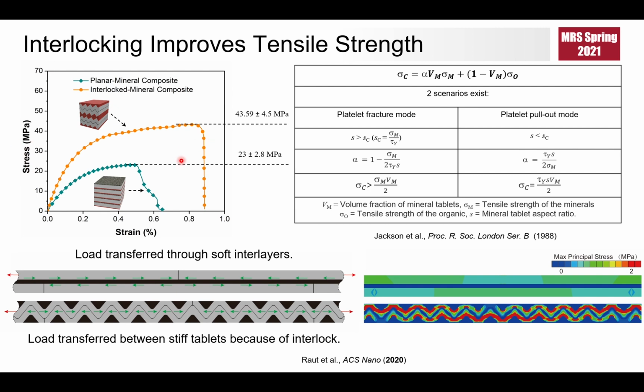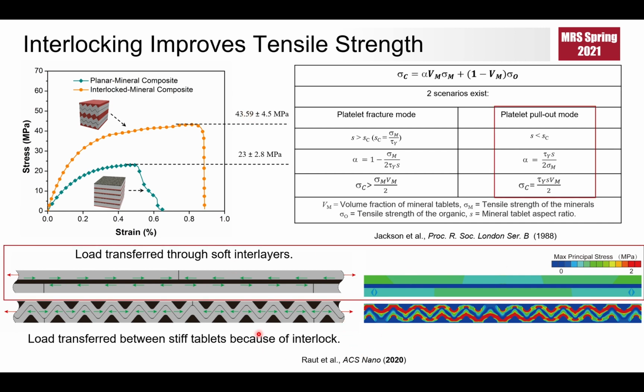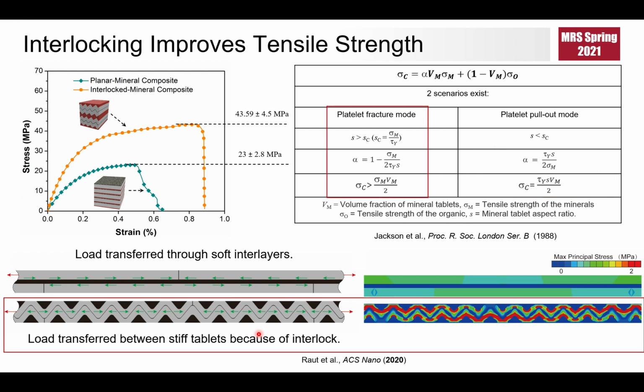Next, we measured the mechanical properties of the composite. As shown in the stress versus strain plot, the ultimate tensile strength of the interlocked composite is about 85% higher than that of the planar platelet composite or the control samples. The finite element analysis of the two composites shows that in the case of the planar platelet composite, in-plane load transfers through the organic interlayers between the platelets, and thus the tensile strength of the composite is proportional to the shear strength of the organic interlayer. On the other hand, in the case of the interlocked platelet composite, the in-plane load transfers through the stiff mineral platelets due to interlocking. Hence, the tensile strength of the composite is relatively higher.